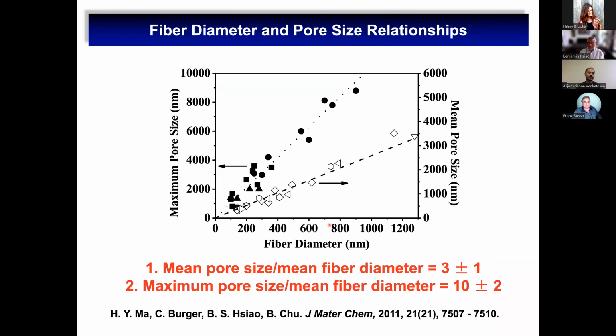And through this research, we also realized there's an experimental rule: with a fiber diameter, plot that against the maximum or mean or average pore size of this membrane. This seems to have a rule that the mean pore size is always about 3 times the fiber diameter. The maximum pore size is about 10 times the fiber diameter. So you can control the pore size of the membranes by your fiber diameter. So this is actually a breakthrough finding.